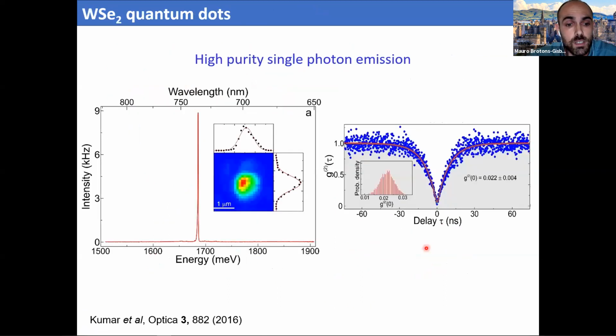So it was, I think, in 2015 and early 2016, demonstrated by several groups that tungsten selenide hosts single photon emitters. Okay, and since then it's been demonstrated that it's possible to have spectrally isolated and spatially isolated single photon emitters in this two-dimensional material, and that these single photon emitters have a very good single photon purity. So since then, people have been trying to deterministically control the number of, let's say, the charge state of these quantum dots,